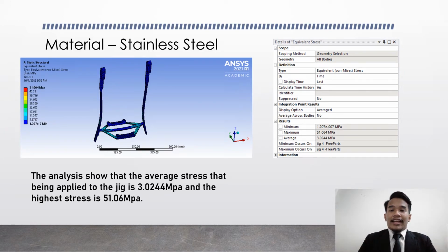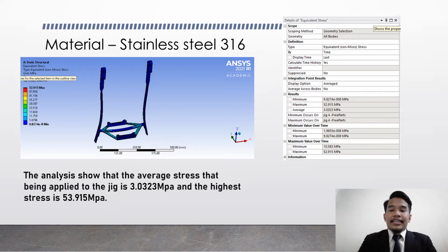The figure shows the analysis for the stainless steel on design 4. The analysis shows the average stress that has been applied to the jig is 3.0244 megapascal. The highest stress for the stainless steel is 51.06 megapascal. The figure shows the analysis for the 316 stainless steel on design 4. The analysis shows the average stress that has been applied to the jig is 3.032 megapascal, and the highest stress is 53.915 megapascal.